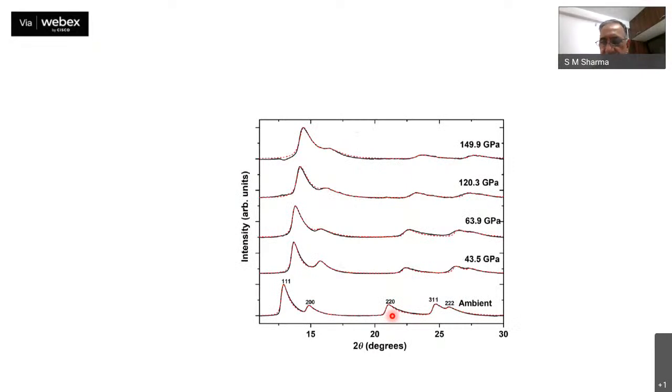The X-ray diffraction pattern absolutely required me to put in a percentage of stacking faults. The reason is that these diffraction patterns cannot be analyzed by normal software, which many of the static pattern people use. One had to write a program into which all inputs go: what is the absorption in a particular direction, how much is the input XRD, the input X-ray profile, what is the nature of the structure, what kind of texture it may have, and so on. All these go in, and the whole diffraction pattern is calculated.